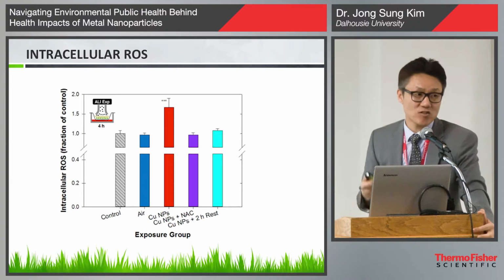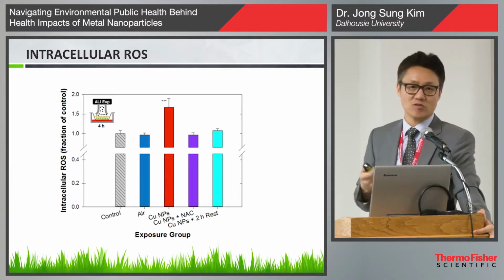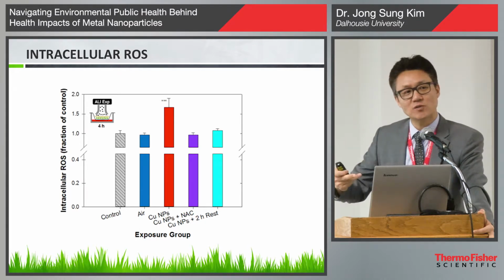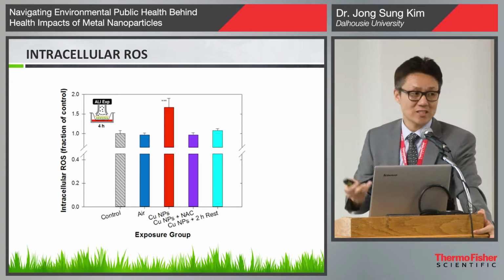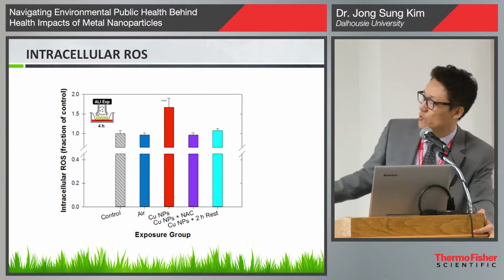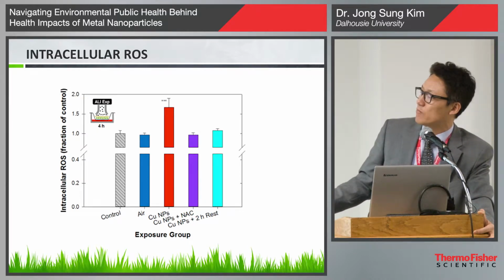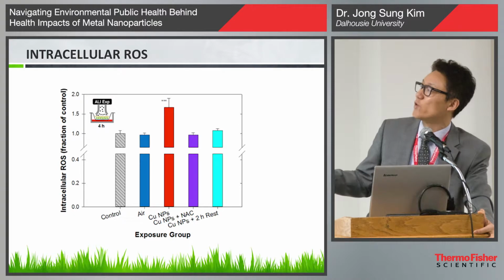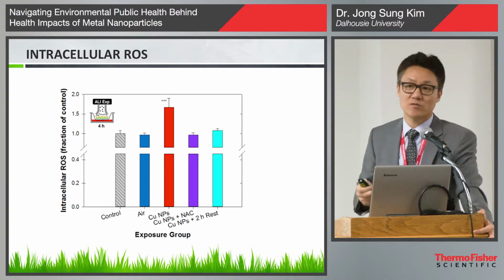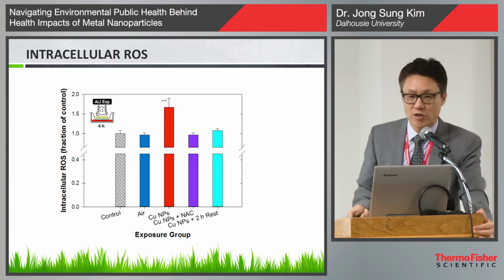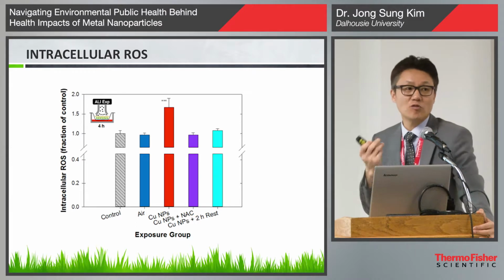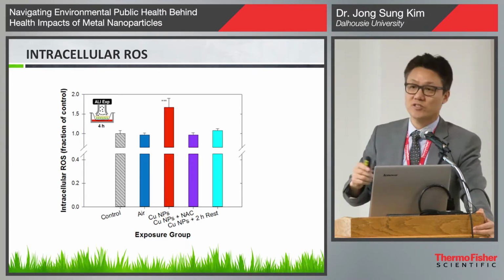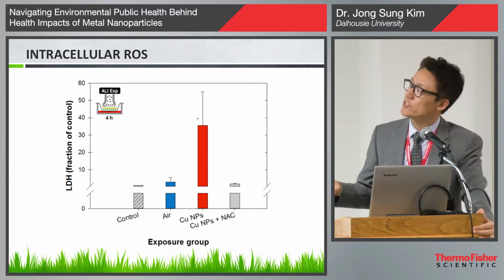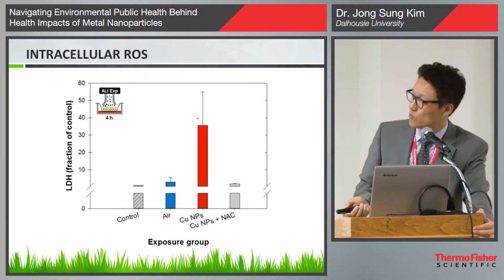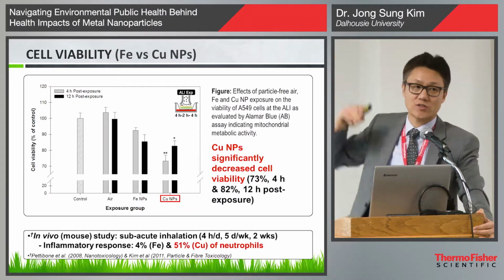Intracellular reactive oxygen species is basically an indicator of oxidative stress. If nanoparticle induce a higher level of intracellular reactive oxygen species, it means a toxicity response. As you can see, compared to control air, the copper nanoparticle exposure induces an increase of reactive oxygen species, which means a toxicity response induced by the nanoparticle exposure, and with NAC, which removes reactive oxygen species, the level is the same as compared to control. LDH is one of the indicators for cytotoxicity as well. You can see with the copper nanoparticle exposure, it goes up.